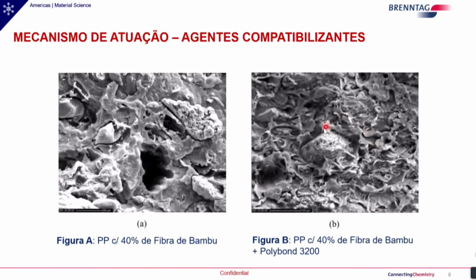Just look at the right-hand side now. When we use this agent, the impact is completely different. You can see that the fibers here are wet, quote unquote, as we call it. This is the term that we use for this type of change in the structure. So this wet stage implies a better binding between the polypropylene and the bamboo fiber.